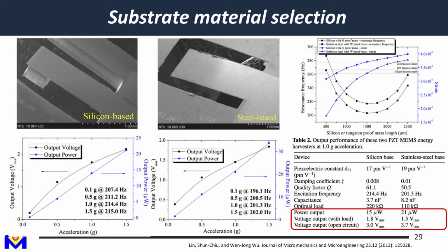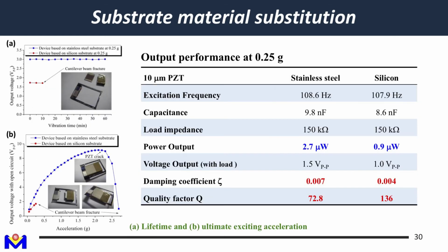So we did a lot of thorough tests. In the end, we proved that for power output and voltage output, under a fair comparison, stainless steel is much better than silicon. And most importantly, the reliability is much better. This is a reliability test for devices, with the blue trace for stainless steel and the red trace for the silicon substrate. When we tested at 0.25 G, the red trace failed after 10 minutes. But the stainless steel one sustained longer than 1 hour. Actually, it could sustain even longer if you extended the test time.